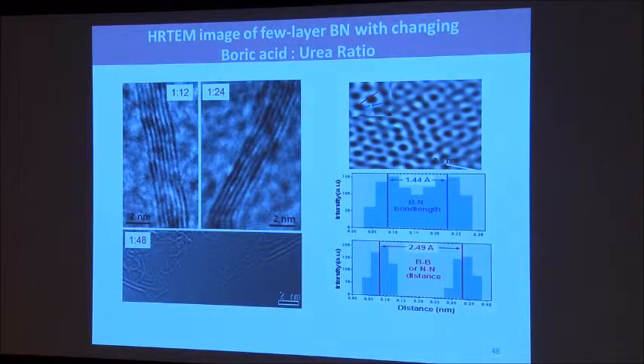You can even measure, with a foot rule, ordinary scale, the distances here, 1.44 angstroms boron-nitrogen bond length. These are few-layer boron nitride, many layers here. They can make single layer, few layer, and so on.